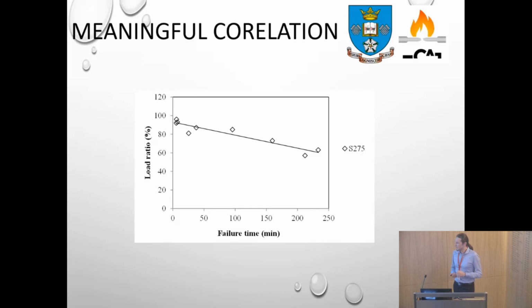I also tried to make some kind of meaningful correlations. These points represent the failure time versus load ratio at different temperature levels. I'm not claiming there is a direct correlation between failure time and load ratio at each temperature level. Just that when you plot these dots in this kind of coordinate system, there's a fairly straight line which connects the increase of failure time with the reduction of the load ratio. So I think this exists for every steel column, depending on its slenderness and the boundary conditions. So I think you can plot something like this for every kind of test that's done on steel columns.